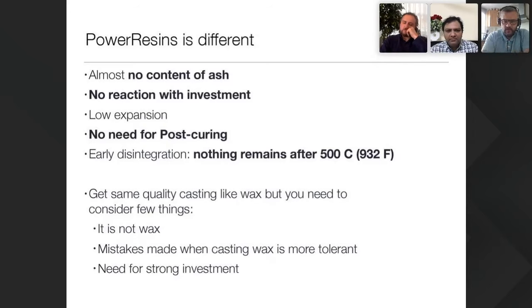They take the flask out of the furnace and then blast it with air. It's not advisable because you're firing cold air into a hot flask. You can get the mold to crack. I think they do this trying to remove the ash remaining from the resin parts. The problem is, I don't know if Stefan tried to burn out a resin part at 800 degrees, but if you do, the ash during burnout reacts with the investment, and that ash stays on the wall of the investment. So the air you put inside may not remove that ash easily. I don't think it's advisable.